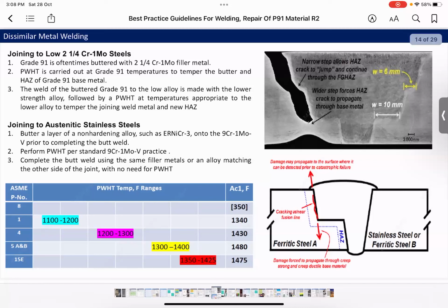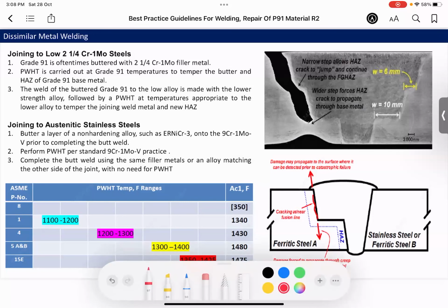So if it's going to propagate, it will propagate through the heat affected zone. So the area here, this area here is the base metal, which has better creep resistance, so it will stop the propagation. But this distance from here to here should be at least 10 mm or higher. So we have common cases where the distance of the step bevel was less than 10 mm and the crack initiated.